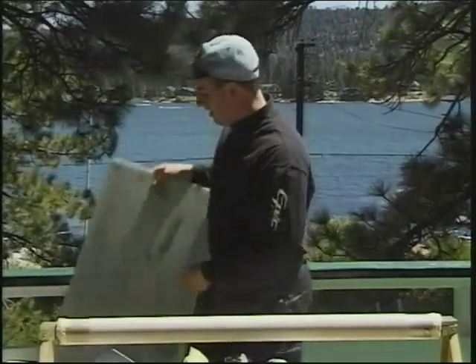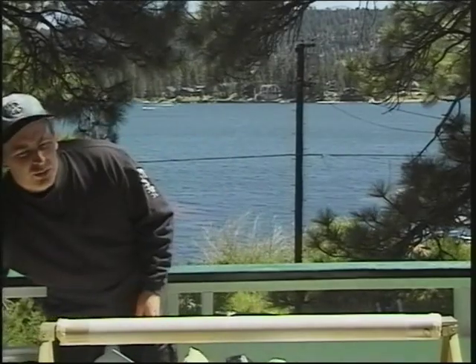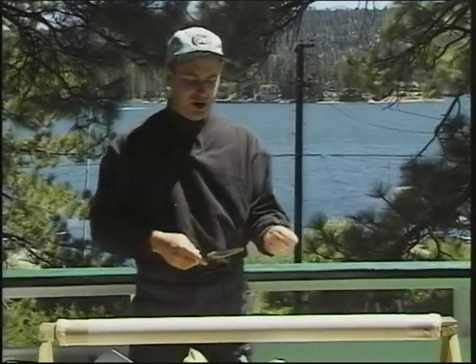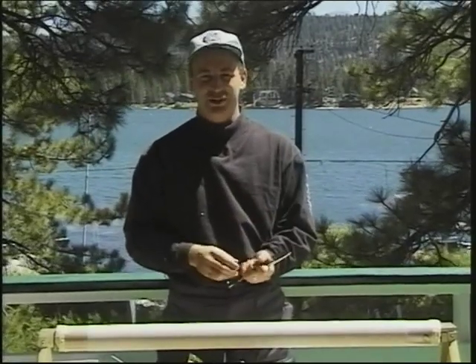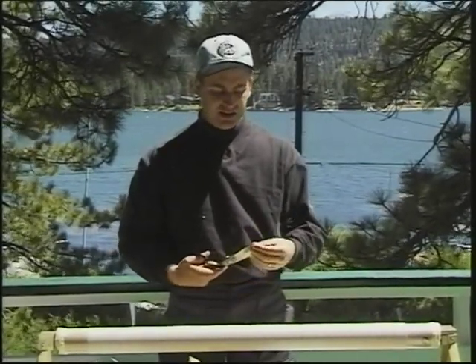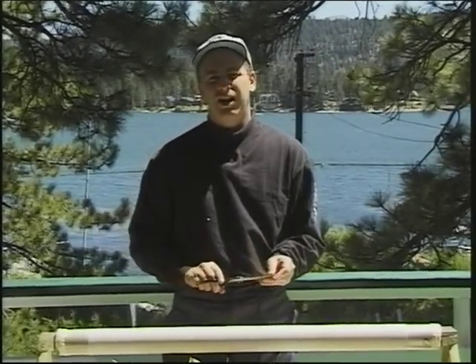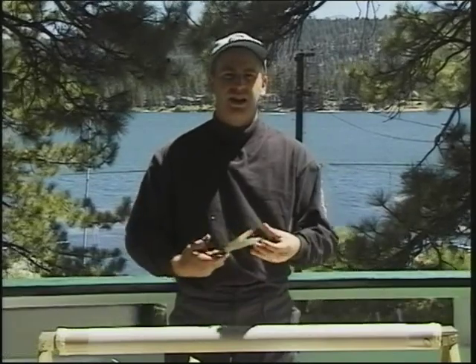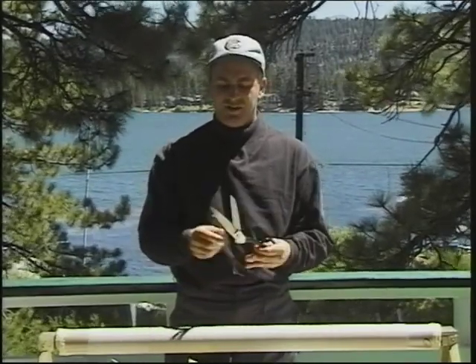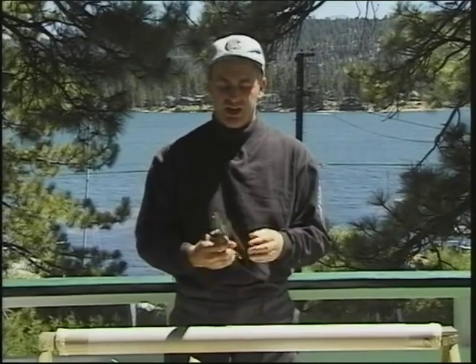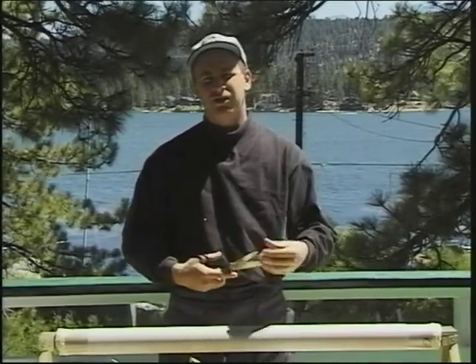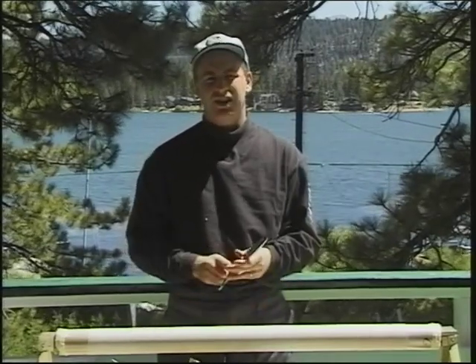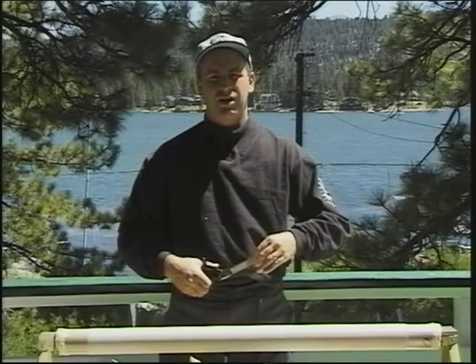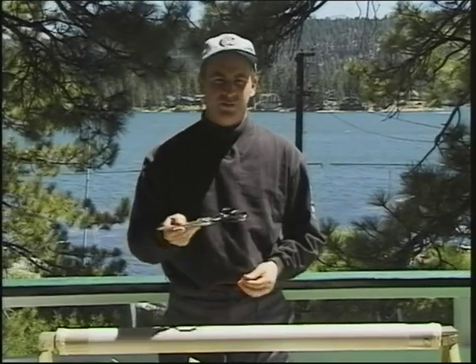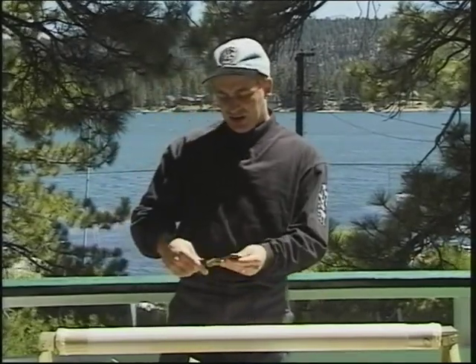When you're cutting Kevlar, however, the reason why they make bulletproof vests out of it, and the reason why they make cut-proof gloves for butchers out of it, is because it's just that, cut-proof. It's very, very difficult to cut. If you're going to be working with any quantity of Kevlar, I'd suggest getting a pair of Kevlar cutting shears like these. They have a special finish on them, and you can get them as inexpensively as $19 from some manufacturers, but you really need this to cut the Kevlar. Any other cutting method will just snag and pull on the Kevlar cloth itself, and you won't be able to cut it. So that's one of the special needs for dealing with Kevlar.